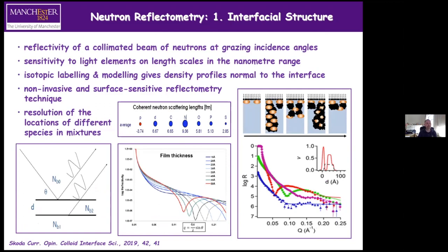The next three slides consider three aspects of using neutron reflectometry to address research problems. The first is the standard way: using neutron reflectometry to look at interfacial structure. Here you have a relatively collimated fine beam of neutrons reflecting off the sample at grazing angles. The nice thing is sensitivity to light elements. Compared with X-ray reflectivity — where sensitivity increases with atomic number — X-rays have little sensitivity to hydrogen.